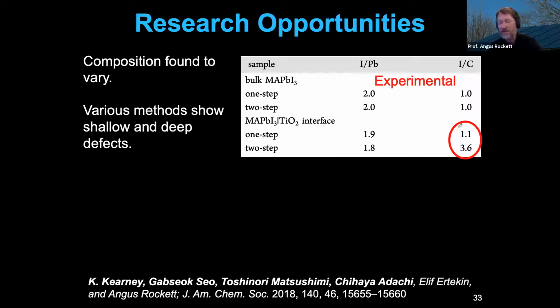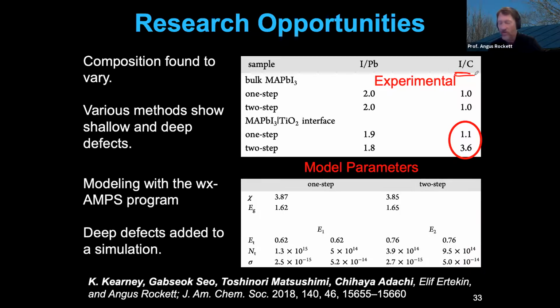And in particular, note that there's a change in the iodine to carbon ratio in these materials for the one-step versus the two-step. And in particular, these are generally deficient in iodine in the one-step process. You can see that the iodine is low. So my part of this was to model the Kyushu results.